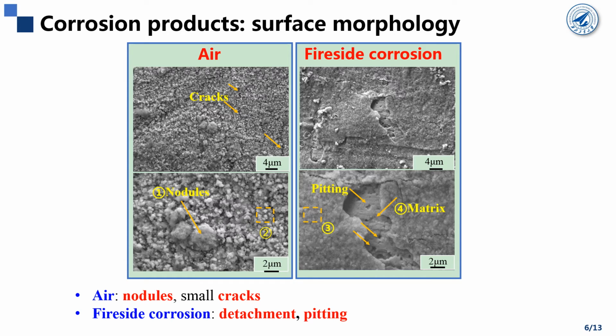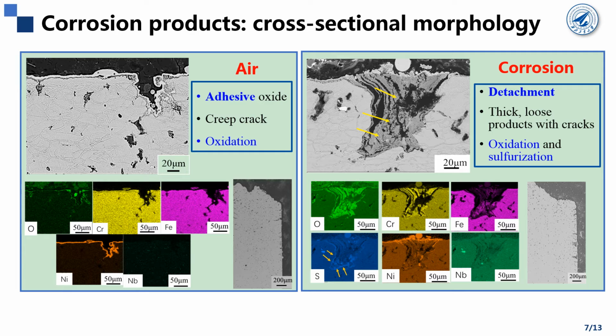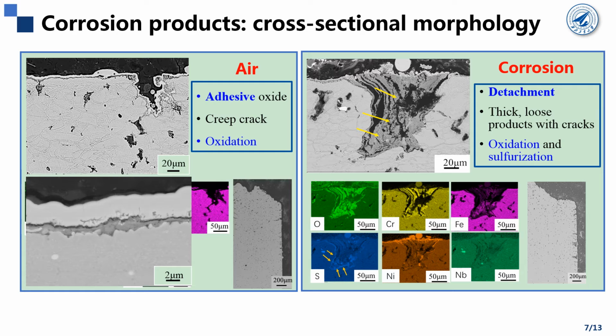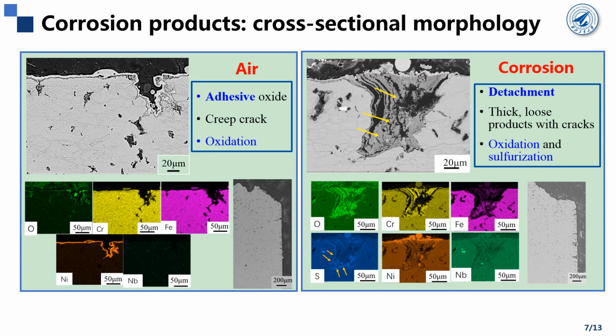Then in this page we go to the cross-sectional morphology. In this global view we can see the oxide layer is very thin and very adhesive to the substrate. If we show more details on the surface layer, we can find the oxide layer is very compact and well attached to the substrate, even along the creep cracks, which are caused by the tensile stress during the creep test. Based on the mapping results by EDS, we can find the oxide scale is mainly composed of chromium-rich oxide.